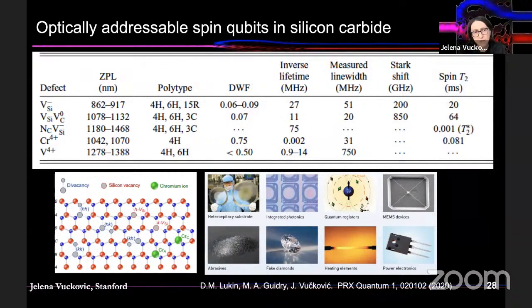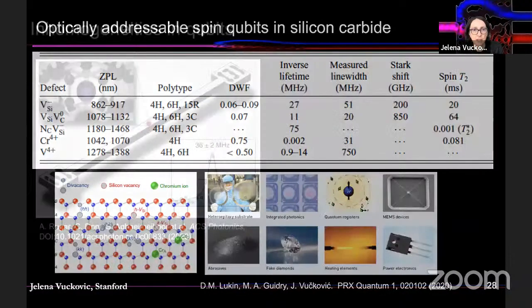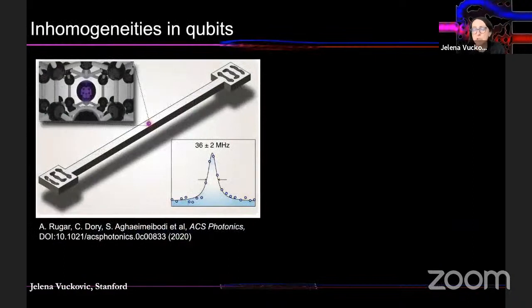So we have been interested in silicon vacancy in silicon carbide, and we've been doing a lot of work in collaboration with Jörg Wrachtrup in Stuttgart because of the good spin coherence properties and convenient wavelength. And we've been looking into it for a number of years, but of course, once you develop the platform, it's applicable to other types of color centers. But as I said, coherence time is long. You can build quantum memories in principle with millisecond storage time. You can do operations with gigahertz speed, but there are problems. Why didn't this system scale to the scales of superconducting qubits or atomic quantum simulators or ion trap-based systems?